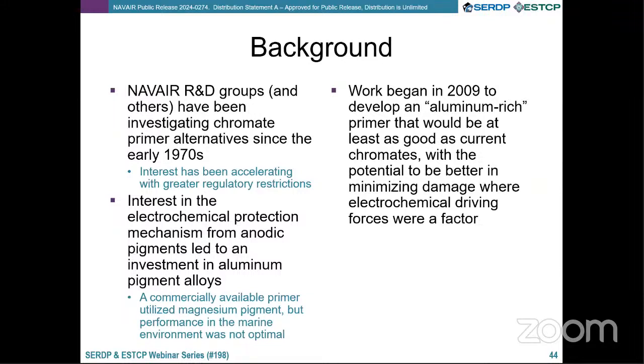Where we got interested in developing the aluminum-rich primer is from the idea that it's not a unique idea either, that there are plenty of coatings that use a protective pigment which is anodic to the substrate. You've had zinc as a coating for steel substrates for many decades, and in the 2000s came to the forefront that magnesium as an aerospace aluminum corrosion inhibitor is a potentially viable anodic material.